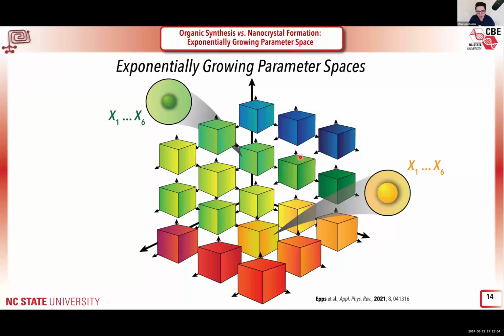Now, an important point I want to highlight here is the difference between inorganic material synthesis and organic synthesis of small molecules. When you're doing any sort of nanocrystal synthesis, there's a nucleation and growth event happening within your synthesis process. This makes it extremely sensitive to the processing parameters: how you heat, how you cool down your reaction, and what the temperature profile of your reaction is. When you do organic synthesis, you start with the same ingredients. It doesn't matter how you heat or cool down your reaction, you're going to get the same product at the end. Now, your yield and selectivity might be slightly different.